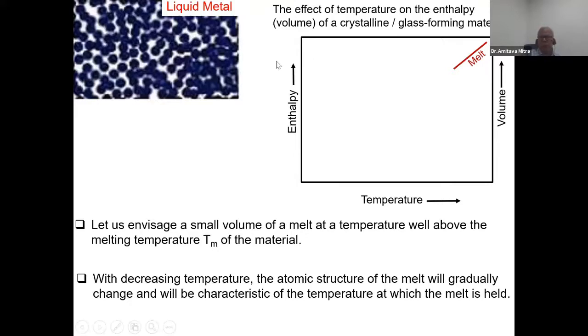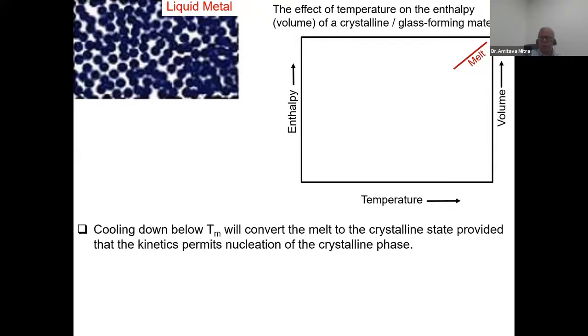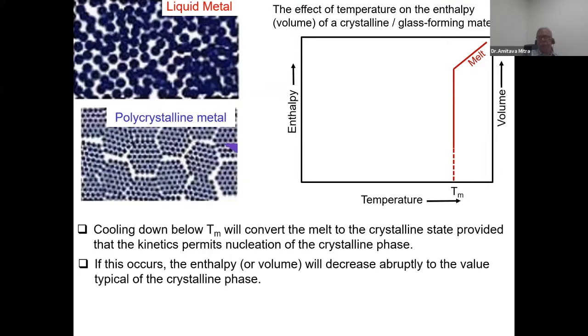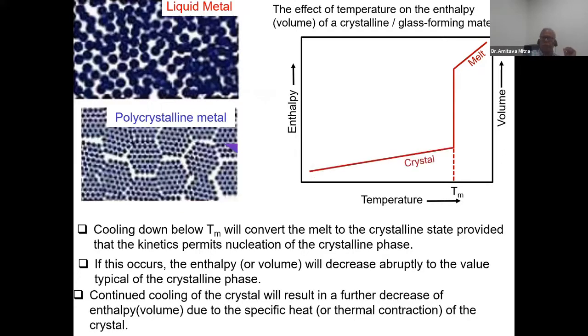Then we cool down, reducing the temperature. When the melting temperature comes, there is a sharp drop in enthalpy and also in volume. If you go further, the volume decreases abruptly, a value typical in the crystalline phase. From there it goes to the crystalline phase, and if you cool the material further, the temperature decreases and the volume and enthalpy also decrease, driven by the specific heat of the solid.